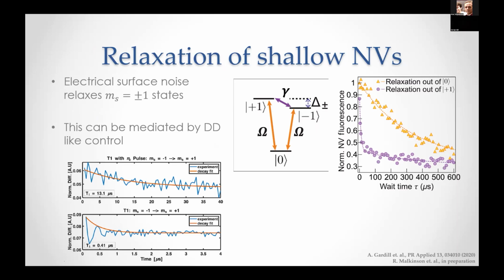So I think that maybe the best contrast that people see is approximately 40% or so, but it is quite common to see contrasts that are much lower than that, on the scale of 10% or even lower. This depends also on whether you're looking at a single NV versus ensembles. So there's a lot of details that I cannot go into all of them. Some of them I understand, some of them I don't. But definitely a big issue with using these systems is that they're real world solid state systems and they're not all alike. Yeah, indeed. Thank you.